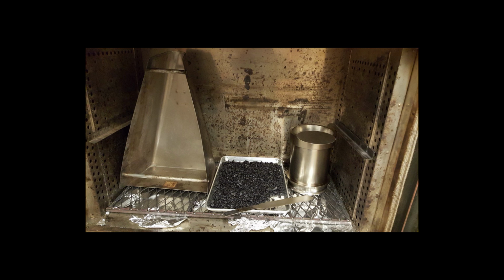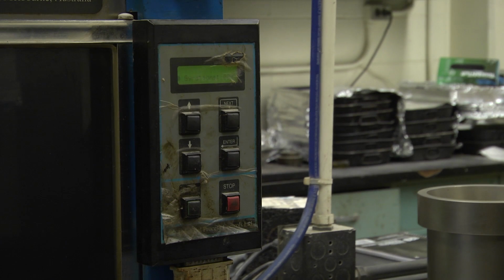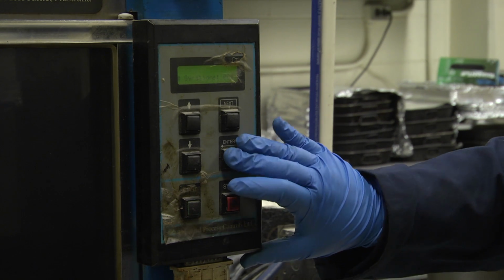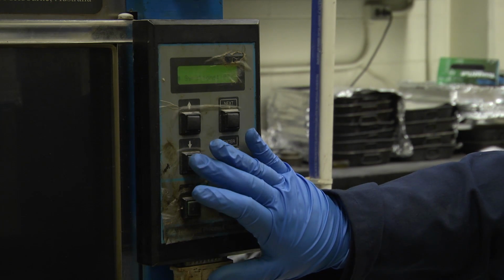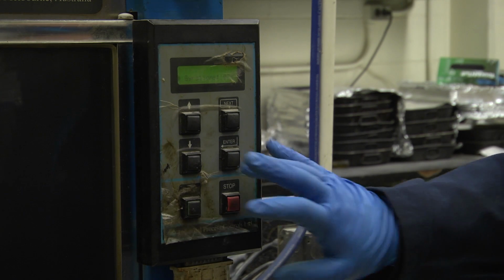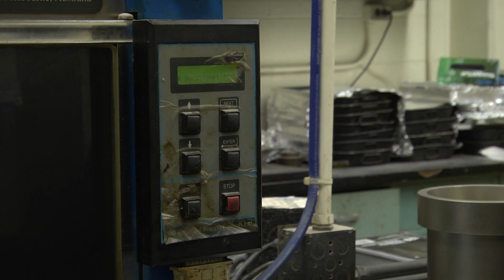Place the gyratory mold, end plates, and mold bottom into an oven set to the compaction temperature at least 30 minutes prior to compaction. Additionally, all other metal equipment that will come in contact with the asphalt mixture, such as funnels, spatulas, etc., should be placed in the oven. Set the gyratory compactor to the desired number of gyrations. The number of gyrations is selected based on design traffic conditions for the mix design.